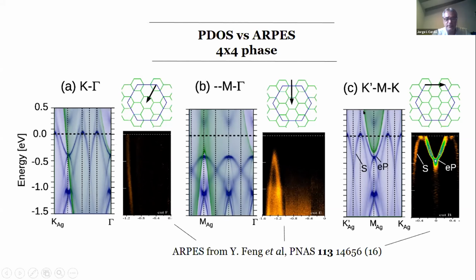It's a gap. This is the only projection of bulk band states. Okay, so they were claiming that this structure here, these two, were the Dirac cones. When we look at what we get theoretically, we get a very nice agreement. This parabola is probably the edge, this intense band that we're seeing here. Maybe some part of silicon around here, this electron pocket, but the surface band that we're seeing here is by no means a Dirac cone. Okay, it's totally covalent, typical covalent bonding with a nice band maximum.